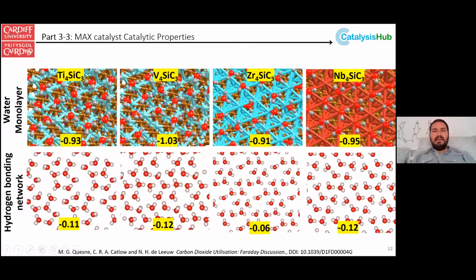So as you can see, this is energy per water molecule for a surface monolayer of water. And what you see is that it's about 1 eV of energy that mostly comes from the preferred binding sites. So we get quite a big difference when we take the surface away and look at the hydrogen bonding per water molecule: a difference between 0.06 eV and 0.12 eV. Obviously the 0.06 eV was the largest surface. So the water molecules sacrificed some of their hydrogen bonding network energy for the preferred binding site of the surface, because that's where most of the energy came from. Again we saw that the surface was very, very reactive, and the water monolayer's geometry was very much dependent on surface geometry.